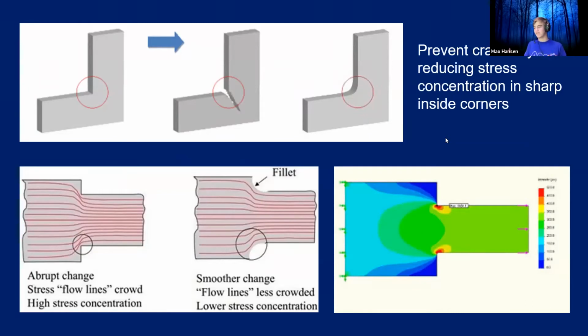As you can see in the bottom left, these abrupt changes cause these stress lines to crowd in these very high stress concentration areas. And then in those areas, the part is prone to breaking and snapping. So then if you add a fillet, you're able to smooth out those curves, and it's much less crowded in those areas, leading to an overall stronger part. This is a fairly small change when it comes to the big picture, but it makes a huge difference when looking at the overall strength of the part.